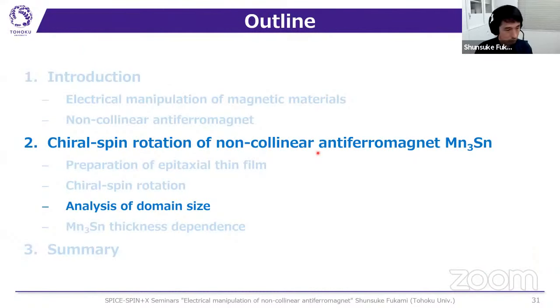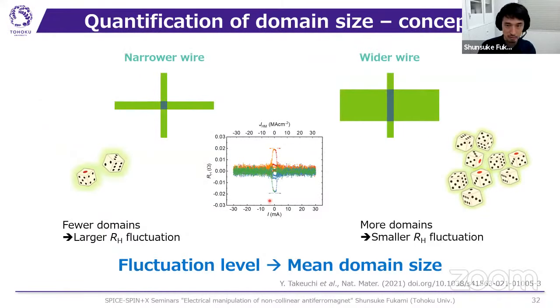Okay, so next I'd like to describe the analysis of the domain size. As I mentioned, the fluctuation comes from the ensemble of the domains accommodated in the whole wire. So we can expect that for a wider wire, because the wider wire contains many domains, many domains should be accommodated in it, so the small Hall resistance fluctuation should be observed. And for the narrower wire, because it contains fewer domains, the larger Hall resistance fluctuation should be observed. So from the analysis of the fluctuation level, it is expected that we can estimate the mean domain size.